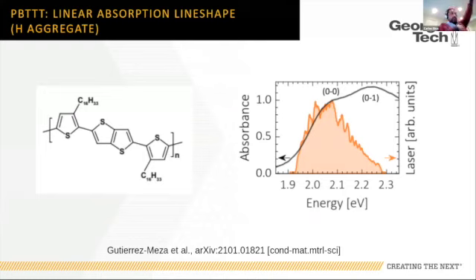So because I'm running out of time, I'm going to quickly just give you the results, and Eric is going to go further into this. I'm going to now look at this polymer, PBTTT. This is now not P3HT. The reason we choose this is because it's like P3HT, but at some high temperature, it's going to have a thermotropic phase transition. It's liquid crystalline. It renders this a very dynamic system. Our line shapes in the 2D spectrum are going to be very well defined because dynamic disorder is going to dominate. And so that's the rationale for choosing this.